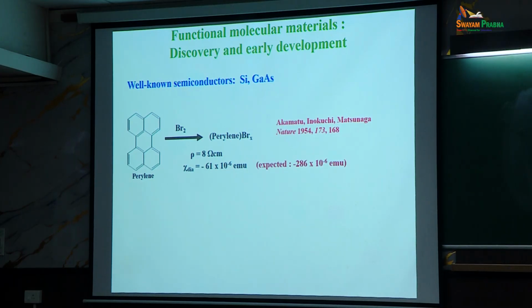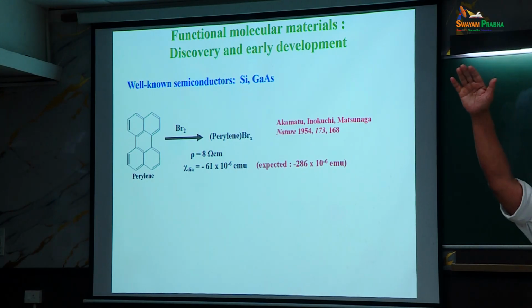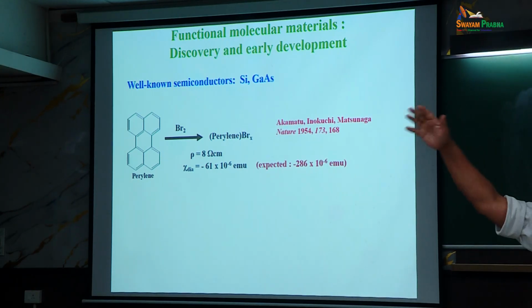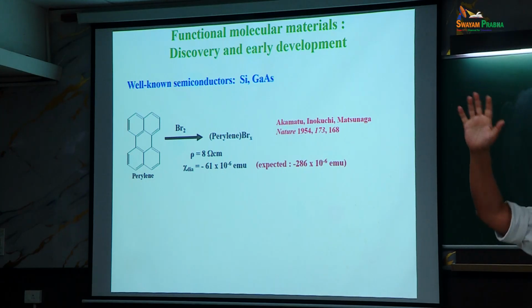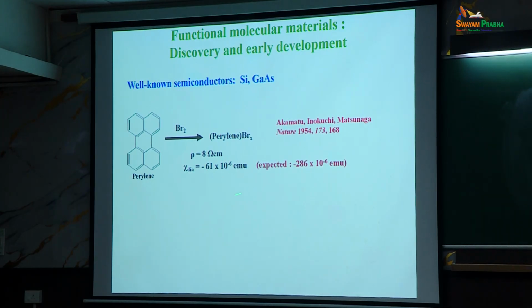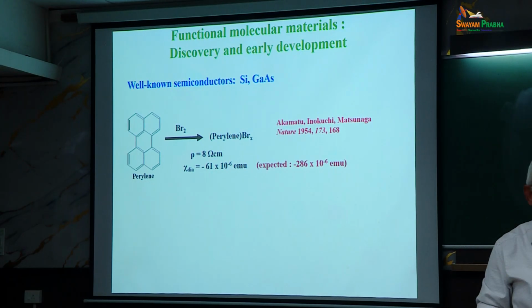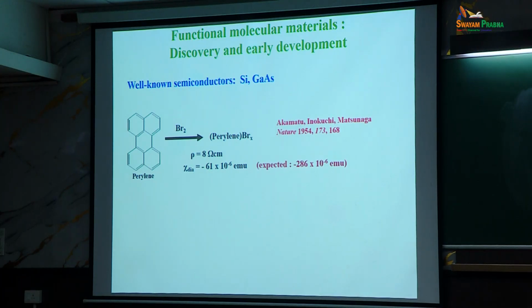They are highly insulating. Their conductivity will be 10 to the power minus 10, minus 12, minus 15 ohm centimeter. So they are extremely weakly conducting. And there is something about magnetic susceptibility, which is also important because these electrons are moving around. They have something called a diamagnetic susceptibility, but it was unexpectedly very different from what was expected. So the expected value is this, and they have a much lower diamagnetic susceptibility.